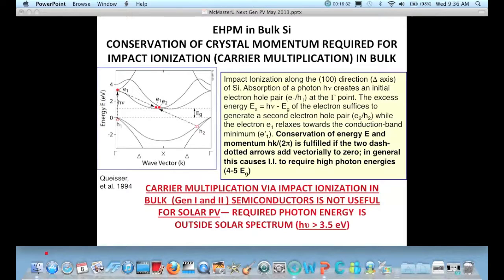And the conservation of momentum is shown here, that you have to excite high in the conduction band of silicon in order to have the change in momentum of the electron exciting, or it's called impacting, an electron in the valence band to excite it across the gap. Those two vector changes have to cancel each other, and that requires this high energy photon.